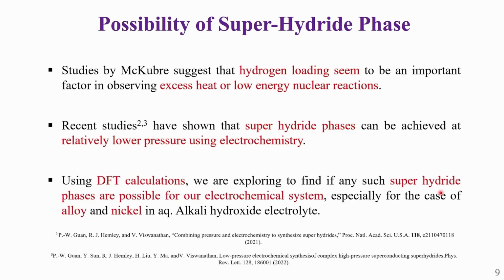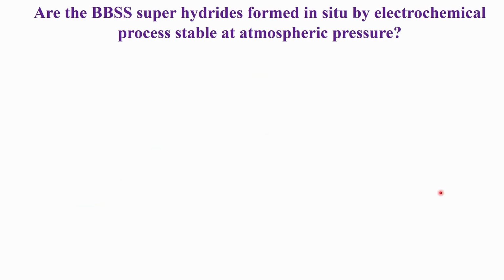In this same line, we are exploring the possibility of superhydride formation in the electrode during electrolysis for the electrochemical system relevant to us, such as nickel cathodes in aqueous alkali hydroxide electrolyte, using computational DFT methods. Are the superhydrides formed in situ by the electrochemical process stable at atmospheric pressure?